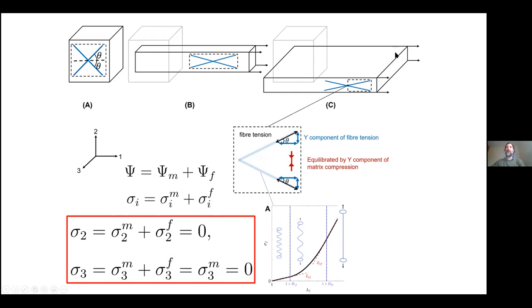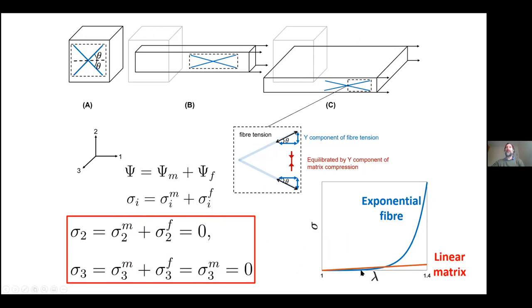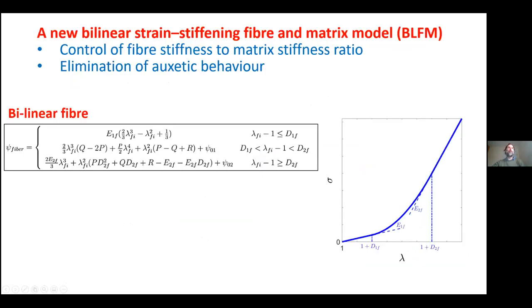And this then forces the matrix to expand outwards in the third direction. So why is this happening? Because the fiber becomes a lot stiffer than the matrix. So if we model the matrix as being linear and the fiber as being nonlinear, then we get these non-physical expansions. And this is called auxetic behavior, where when we stretch the material, it expands outwards.